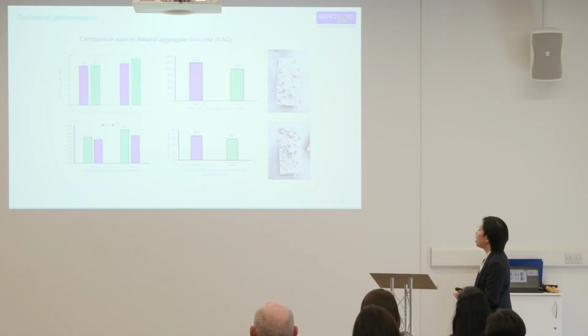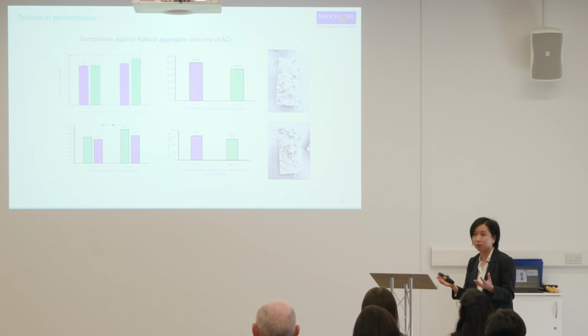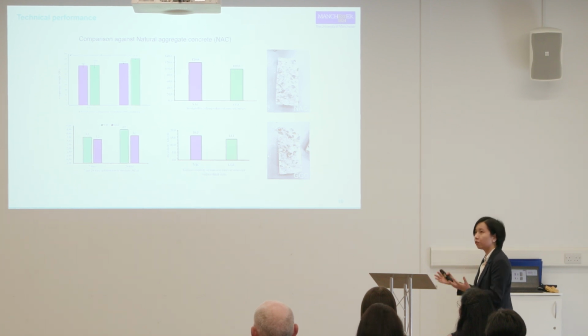So in order to demonstrate that, we have done quite a lot of comprehensive experimental program at the laboratory to investigate those fundamental properties of the graphene green concrete first, and also compare them against the natural aggregate concrete. All of the results tell us that graphene green concrete actually can achieve comparable properties to natural aggregates, and also those fundamental properties like compressive strength, tensile strength, workability, surface resistivity, and failure modes. They can all satisfy the industry's requirements.